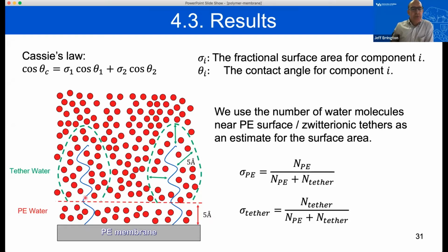And so what we did was to identify different regions and associated water with either the tether or with the base surface. And so just based upon an analysis of different snapshots of water in the vicinity of these different polymer tethers, we were able to determine the fraction of water in this case that is in the vicinity of a polymer tether versus that of the membrane. And the whole idea of Cassie's law is to say that the cosine of the contact angle of a fluid on some composite surface, so a surface made up of multiple materials, is given by this linear combination of the surface fraction associated with component 1 multiplied by the cosine of the contact angle, and the surface fraction of component 2 multiplied by that contact angle.